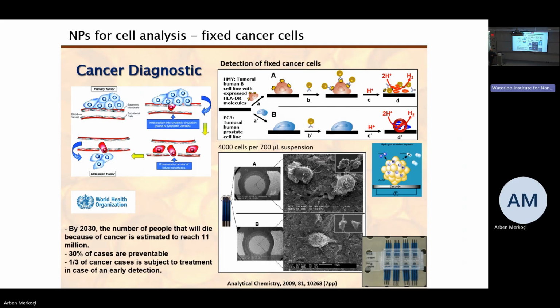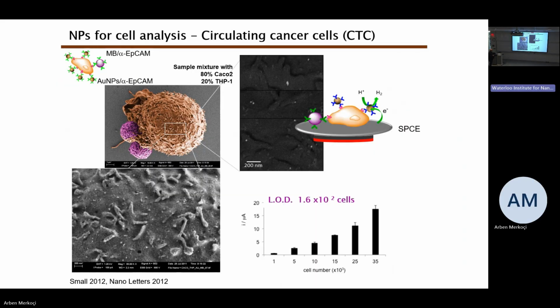But of course, this does not reach the detection limits that we want for cancer cells. We try to push these improvements toward reaching lower detection limits. And as you can see here, we used some magnetic beads to capture the cancer cells. The magnetic beads, in violet, which is a fake color, again work through the interaction of antibodies.